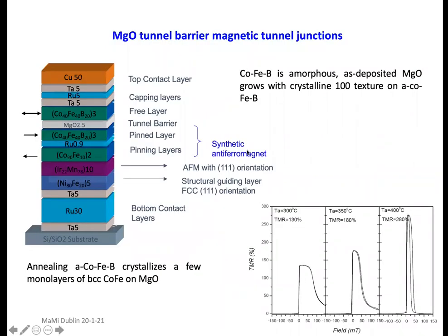Now, these stacks are not quite as simple as they appear. This is a real stack that you need for a magnetic tunnel junction. You can see it's got about 14 different layers. Right here in the middle are the two magnetic layers separated by the thin tunnel barrier, which is of order a few nanometers of MgO. I don't have time to explain this or to parse it, but you can see that these devices really required rather sophisticated thin film growth.